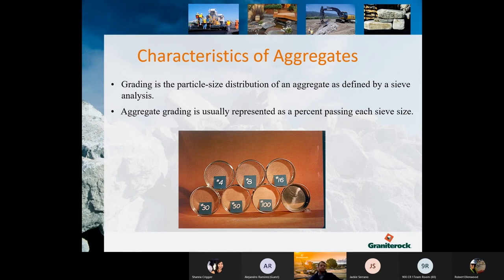Characteristics of aggregates. Aggregates are usually described by their gradation, and grading is the particle size distribution of an aggregate as defined by a sieve analysis. So here you can see below, this is for a fine aggregate. The numbers represent the number of squares in a square inch. And what happens is you stack these rings on top of each other, starting with 4, followed by 8, 16, et cetera. You place the material on the top, and then you shake the sieves all together, and material will be held on each level. And then you come back and record how much is there. So it gives you the distribution of the particle size on each sieve.